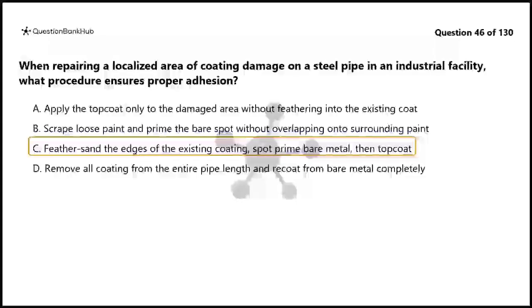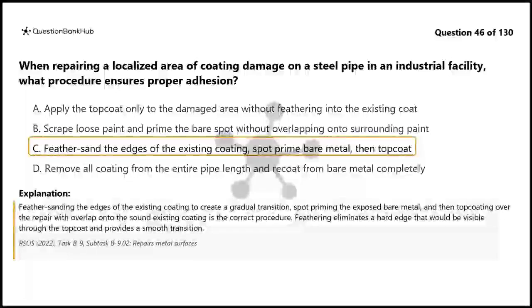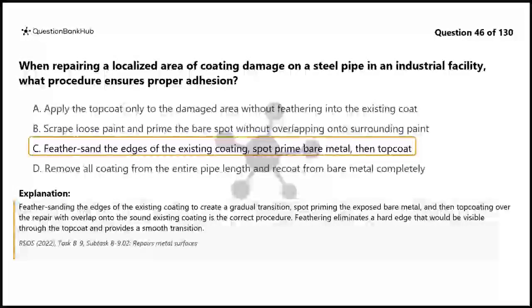The correct answer is C. Feather sanding the edges of the existing coating to create a gradual transition, spot priming the exposed bare metal, and then top coating over the repair with overlap onto the sound existing coating is the correct procedure. Feathering eliminates a hard edge that would be visible through the top coat and provides a smooth transition.